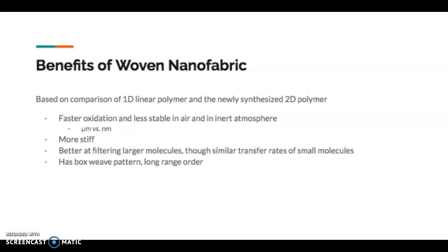And the 2D polymer was more stiff, determined as having a Young's modulus of 7 gigapascals. Nylon and other polymers had moduli of 2 to 4 gigapascals. Additionally, the two-dimensional nanofiber was better at filtering bigger molecules, specifically the iron(II) circular helicate, than the one-dimensional polymer, although both were able to similarly filter a smaller iron(II) phen complex. And again, in comparison to the one-dimensional, the two-dimensional has the box weave pattern and the long-range order.